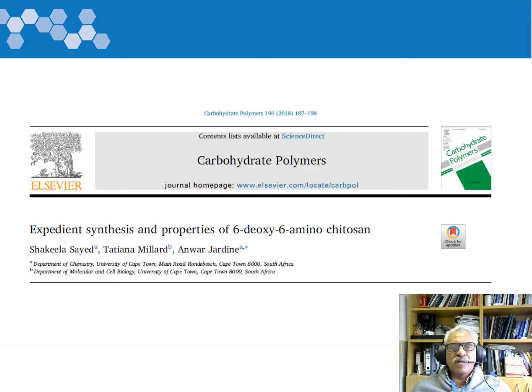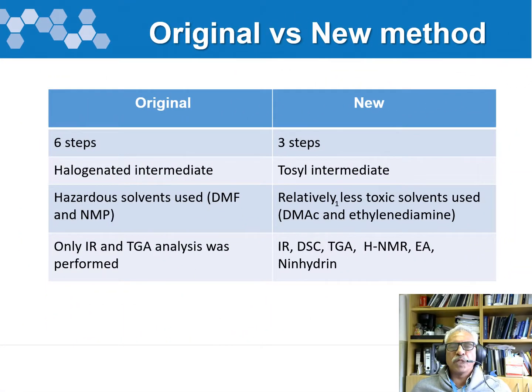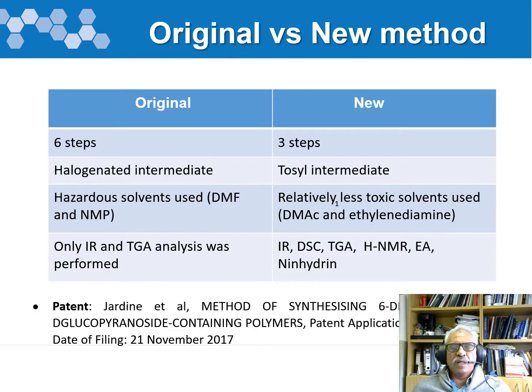This work was published in Carbohydrate Polymers. So the improvements here: the original method used 6 steps, we narrowed down to 3. It used a halogenated intermediate, which is not very green, so we went for the tosyl. Some of the hazardous solvents used were DMF and NMP. We switched to DMAC, which is less toxic. And of course, earlier work used very few analytical methods to characterize it. We've done a much more rigorous characterization, and of course, the work has been patented as well.